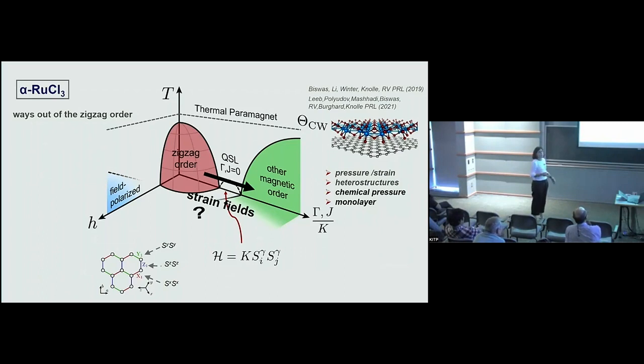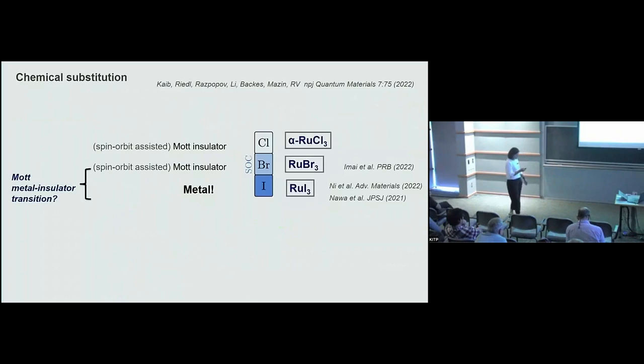You can, for instance, create heterostructures that strain the alpha ruthenium trichloride appropriately, depending on which substrate you are using. There has been a lot of work, and Eric, who is here, has done a lot of work on this type of heterostructure, alpha ruthenium trichloride on graphene. But what I want to discuss today is two other types of negative pressurizing of the system, which is by applying chemical pressure, and I also want to show very recent results on just monolayers of alpha ruthenium trichloride, which show very interesting surprises. So what happens with chemical substitution?